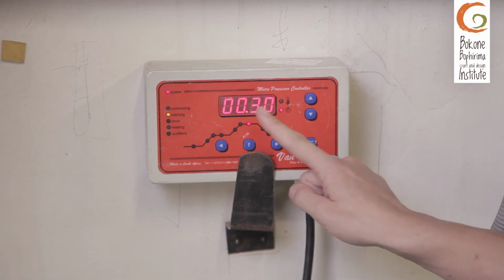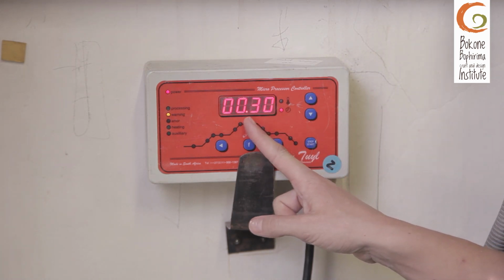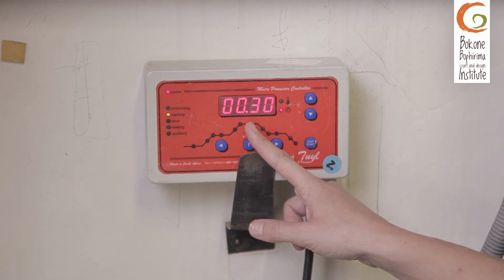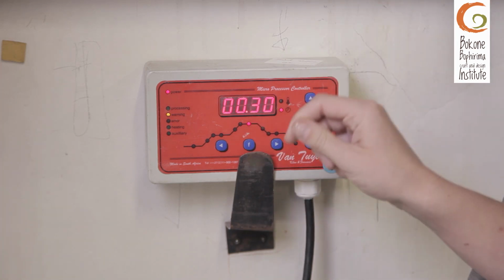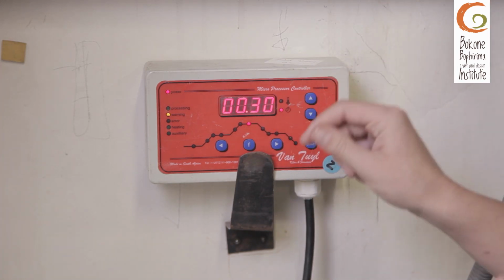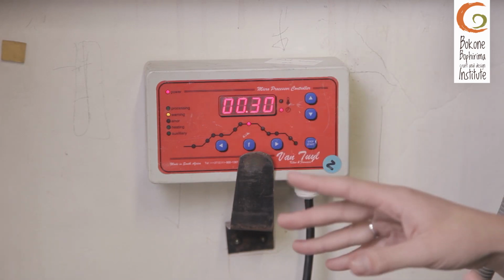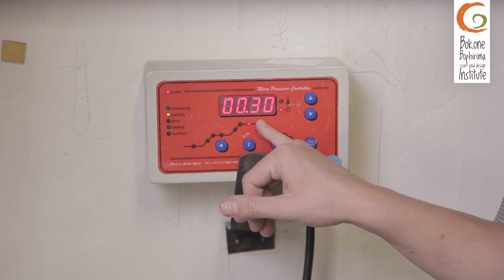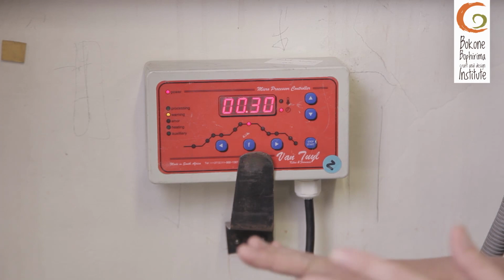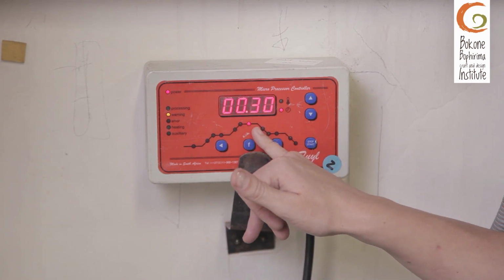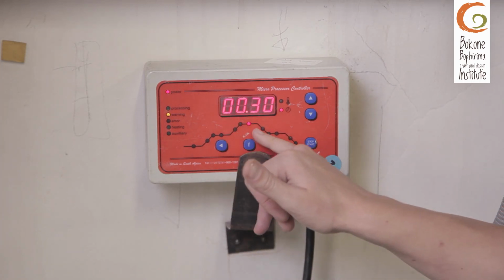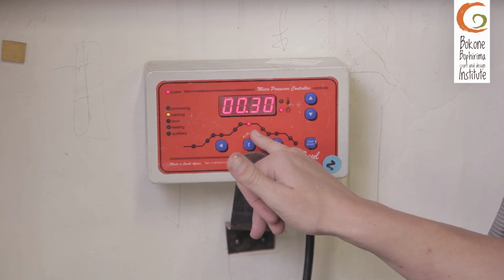One can also, in this process, especially with slumping, just before you hit your 30 minutes, peek open the lid of the kiln and double check that you are happy with your desired shape that you have. If you feel it has not completely slumped into the mold, rather quickly go back into your program and allow it to hold longer at that top temperature.